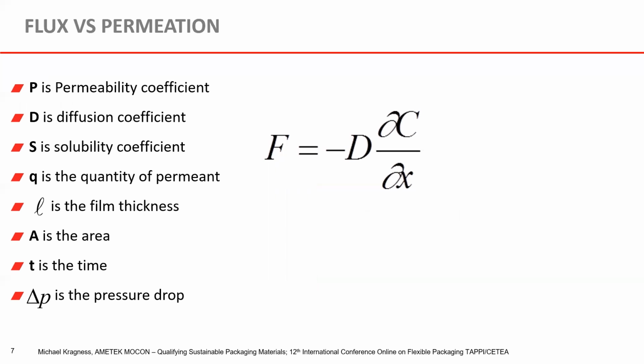Just to speak a little bit further about permeation testing, flux and transmission rate. In the industry, transmission rate and permeation rate are often used interchangeably, but they really are different. Fick's first law has to do with the transmission rate of a material, where you're measuring the flux coming through some film or some sidewall of a package. You have your diffusion coefficient for that material, and then you have the concentration gradient, or the rate of change of the concentration over some distance. This distance could be the thickness of a film or a package sidewall. In this case, you're just measuring the volume of gas that's coming through some structure.